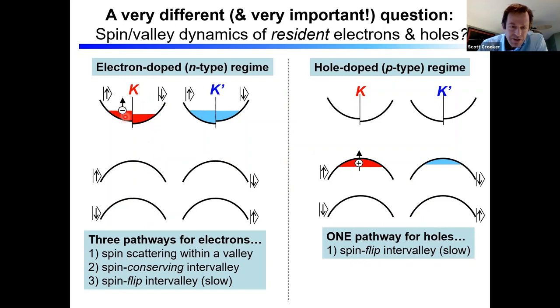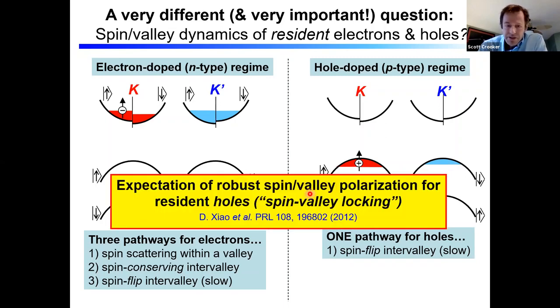And so there are three pathways to relax. I could have spin scattering within a valley. I could have spin preserving scattering between valleys or some combination of the two. But for holes, because of this gigantic spin orbit coupling, in order for a hole to relax or scatter from here to here, it has to not only scatter across the Brillouin zone from K to K prime, but also has to flip its spin. So in that sense, it's doubly prohibited. And there's always been an expectation that this should lead to a very robust spin and valley polarization, particularly for holes, coming about from the spin valley locking. So that's what we're going to try to measure.